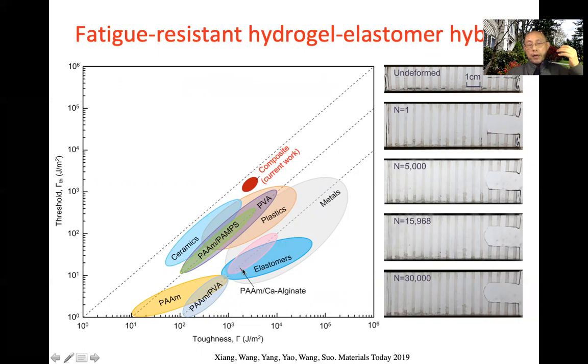Various ways of enhancing elastomer, for example carbon black or silica particles, do not change the threshold very much. You can change toughness enormously, but the threshold is still on the order of 100, less than 100 joule per meter squared. However, our material goes to a high value of threshold.